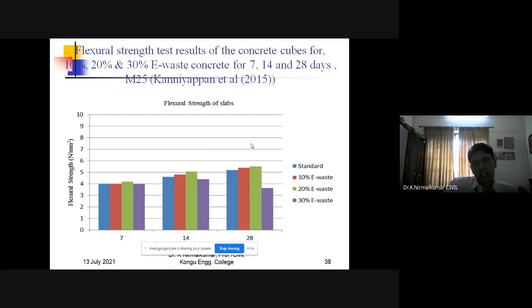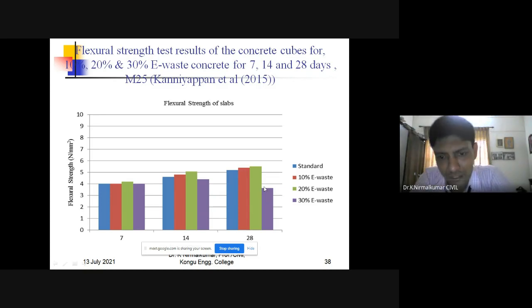Then he also gave the inference for the flexural strength, and here the flexural strength is also good. Let us discuss only the 28 days strength. The conventional is around 5 Newton per mm square, whereas the 20% replacement and 10% replacement are a little bit more than the conventional one, around more than 5.3 Newton per mm square. Here I think he did it for slabs. He had a comparatively good result, because we always have to compare with the conventional one.